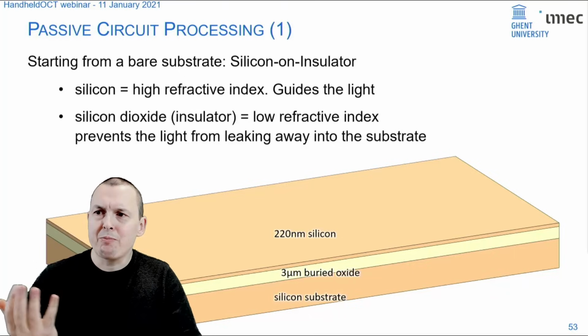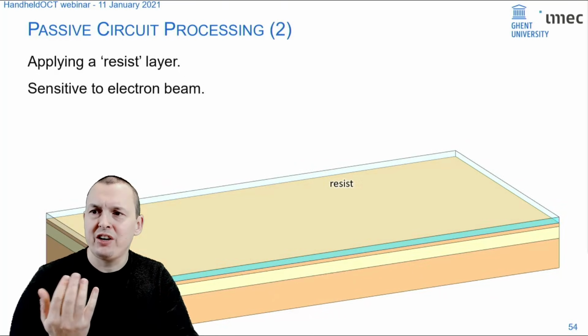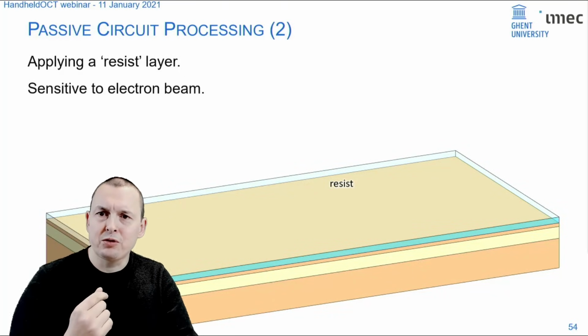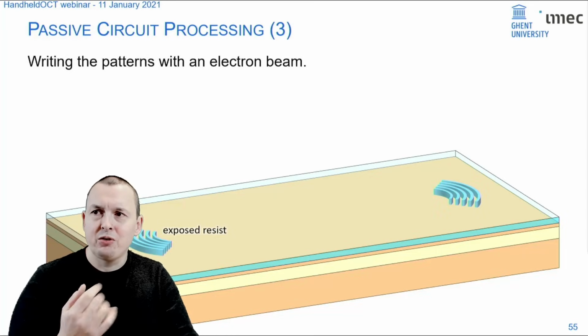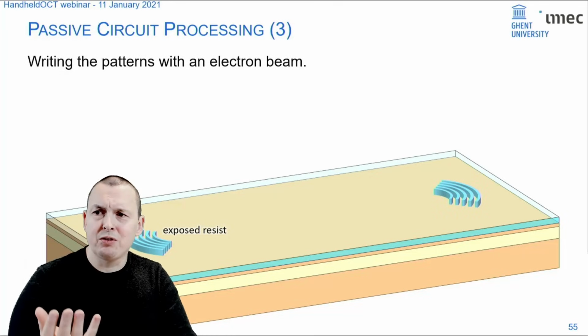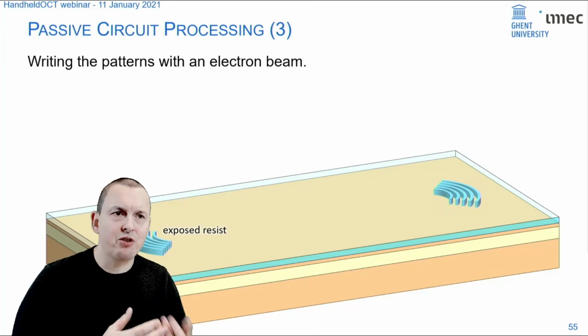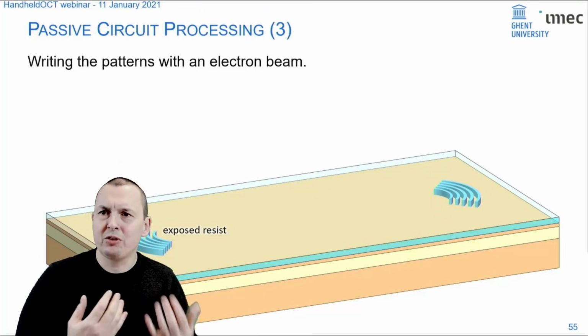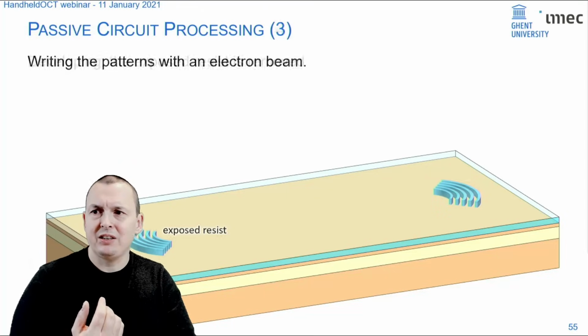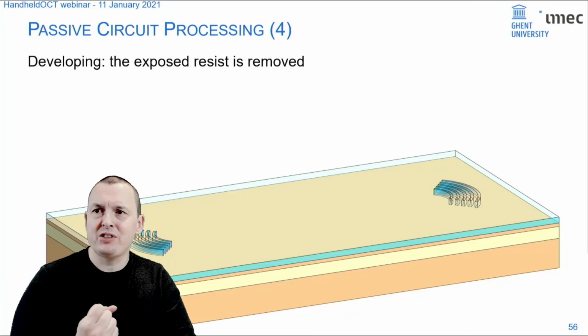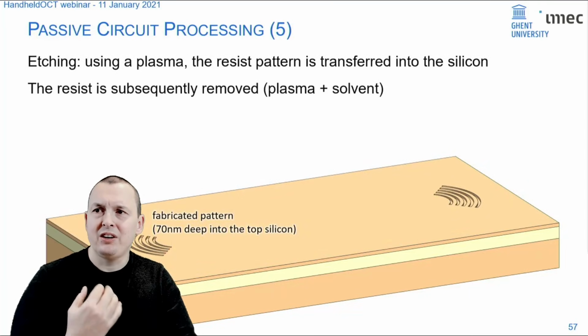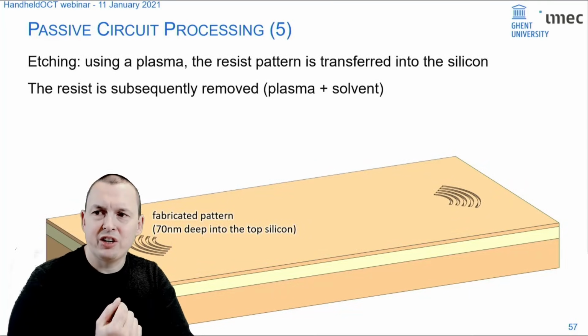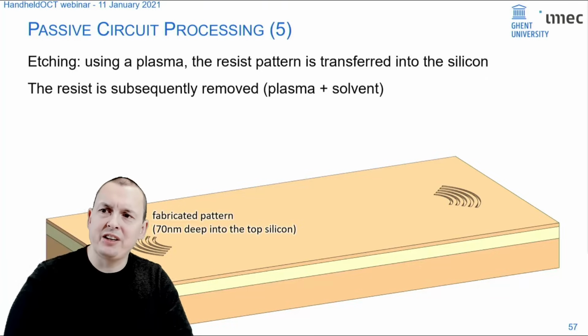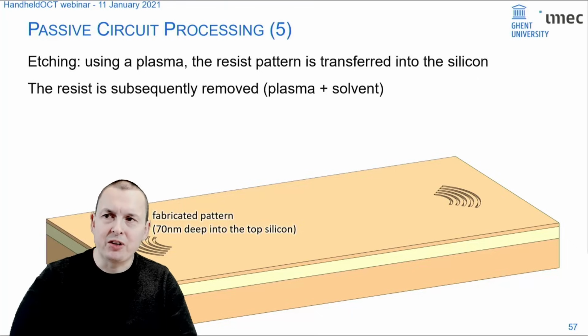Now, if you want to create patterns in these, you essentially start with coating a photosensitive resist. You imprint a pattern in the photosensitive resist. This can be done with an electron beam, or with an optical stepper. Then you develop that resist, and then you use reactive ion etching to etch away the silicon in the exposed areas. In this case, for instance, you do a pattern of a grating, which is etched 70 nanometer deep.